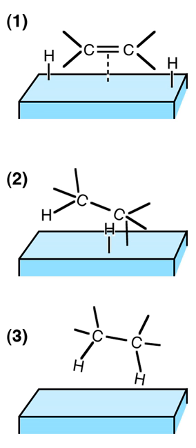Topic: Heterogeneous catalysts. Heterogeneous catalysts for hydrogenation are more common industrially. In industry, precious metal hydrogenation catalysts are deposited from solution as a fine powder on the support, which is a cheap, bulky, porous, usually granular material, such as activated carbon, alumina, calcium carbonate or barium sulfate.